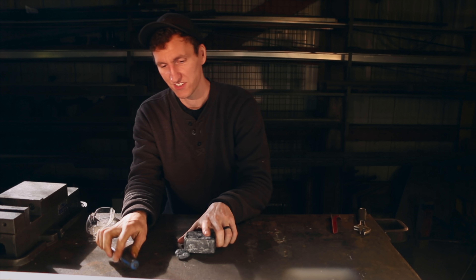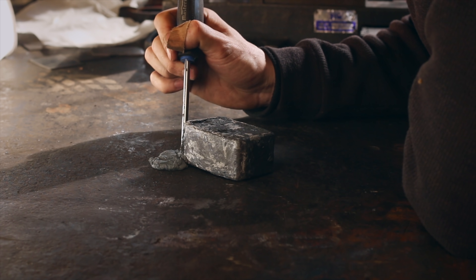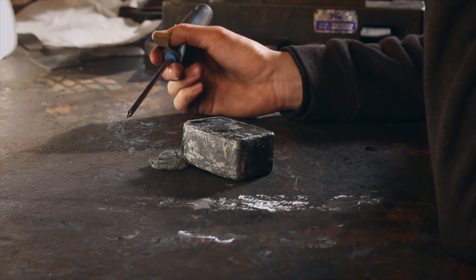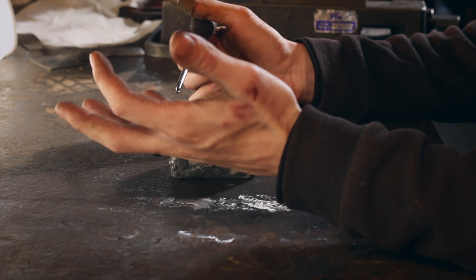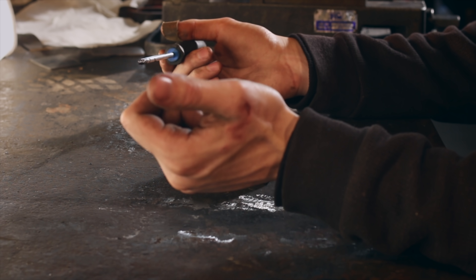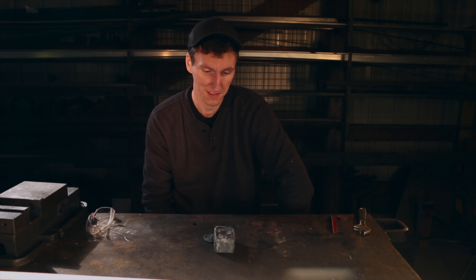So this is cooled off now. Thought we'd take a closer look at this — all this molten metal came out. Super glad I did not go to the power hammer, because if I had tapped that on the power hammer we would have blown molten metal everywhere. It would have completely blown this thing apart. I wish I had done the first heat, let it cool out of the welding temperature, and then tried forging it. I want to cut it open now and see what this looks like. I feel like whether it worked or didn't work, we'll still be able to determine that by cutting it open. I feel a little disappointed with where it's at, but at the same time it's the first one — we're figuring this out. Really excited to cut it open and see what it looks like.